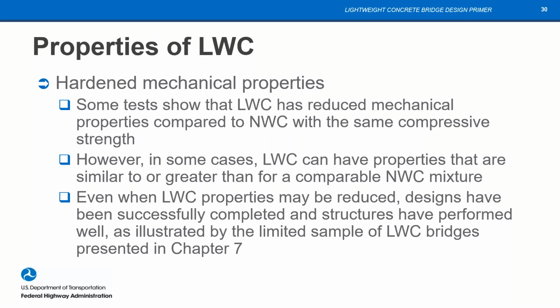as well. But what about the hardened mechanical properties? Some tests do show that lightweight has a reduced mechanical property compared with normal weight. But in some cases, lightweight can have properties that are similar to, or maybe even greater than a comparable normal weight mix. But oftentimes, even if a lightweight concrete property may be reduced, we can modify our designs in some way to deal with that. One thing is, for example, a research test where they keep all the parameters the same and they just swap out the rock. You're going to have a lower strength in lightweight concrete than you do in the normal weight. Not a lot, but you will have some reduction.